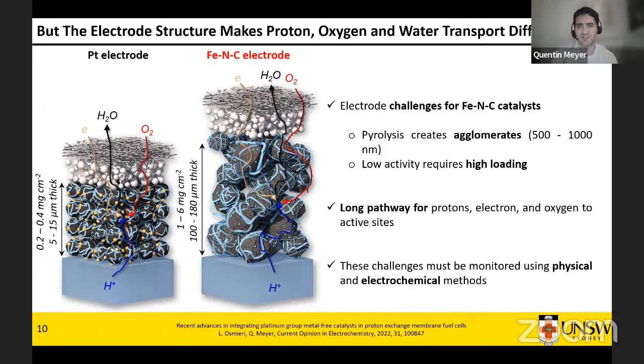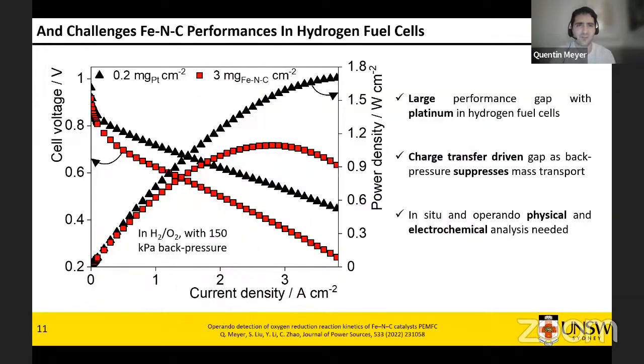So what you want to do is monitor this challenge using physical and electrochemical methods to actually figure out what's happening. So this is what happens when we test my catalyst in a fuel cell. On the left side, it's called a polarization curve. On the right side, on the right arrow, it's called power density. You get somewhere around 1.8 watts per square centimeter in oxygen with back pressure for platinum, if you use a fully commercial cell, you probably get somewhere around 2.4. And our own catalyst, Fe-N-C, gives us somewhere around 1.1 watts per square centimeter with back pressure and hydrogen oxygen. So that's a good start, but there is still a very large gap, about 700 milliwatts per square centimeter.